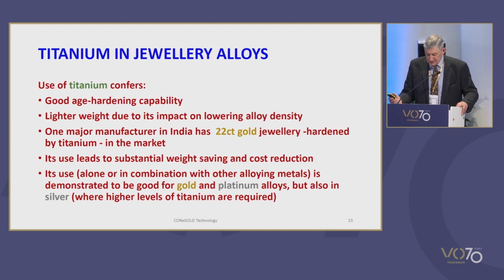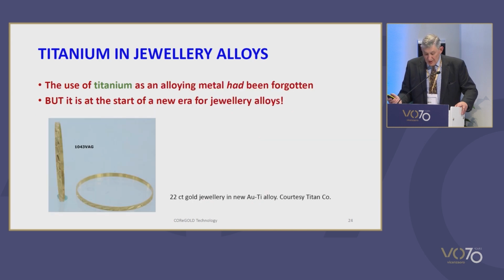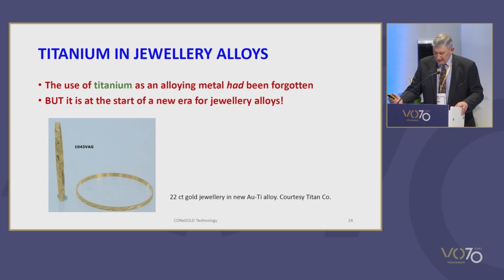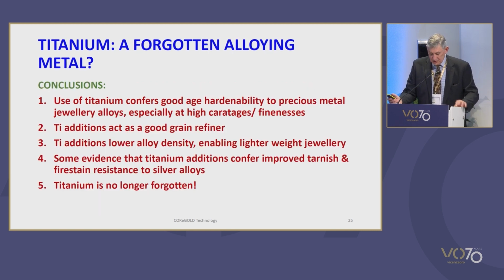From the evidence presented in this paper, the use of titanium alone or in combination with other alloying metals facilitates good age hardenability for gold and platinum alloys particularly, but also in silver, albeit high levels of titanium additions are required for silver. There is evidence that it also confers improved tarnish and fire stain resistance to silver. So to answer the question posed by the title, the evidence is that titanium as an alloying metal had been forgotten, but it appears to be at the start of a new era in its use in precious metal jewellery alloys. So we can make the following conclusions, I think.